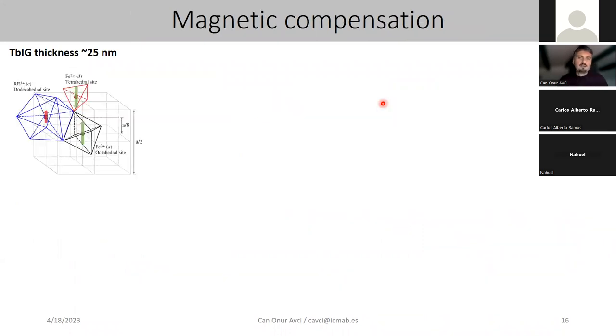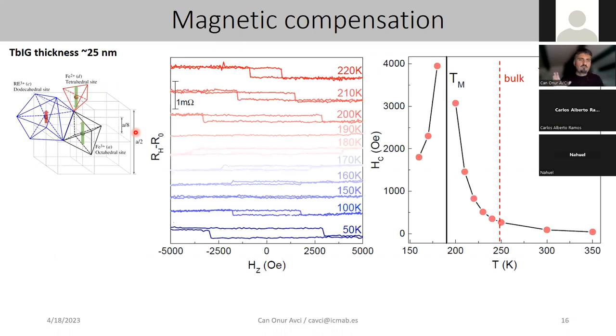Okay. So one important aspect of this terbium iron garnet, as I mentioned briefly before, is that it also shows some magnetic compensation at a certain temperature. One way of measuring the magnetic compensation in these films is checking the coercivity as a function of temperature. When the magnetization is compensated, the film should act like an antiferromagnet, and the coercivity should diverge because of the vanishing Zeeman energy on the net magnetization. So this is what I'm showing you here.